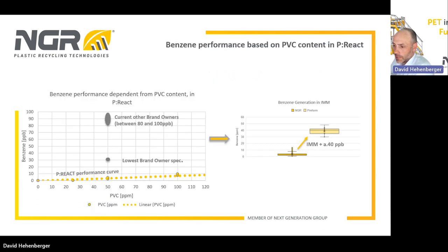But these results fit excellently to what we found in our test center. We did a test with virgin PET, and we purposely added PVC in order to find out what the performance of the liquid state polycondensation is.